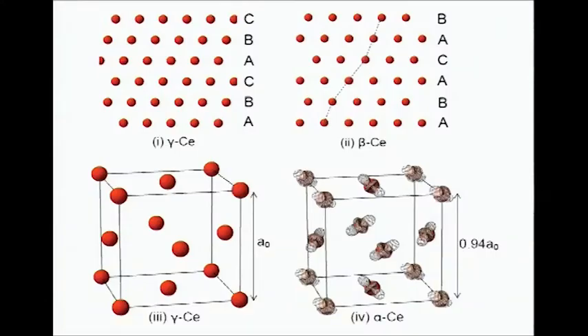Finally, some recent experiments by a Russian group showed that the alpha phase is actually a quadrupole ordered phase, and you get the right lattice constant. They measured this by perturbed angular correlation, and they had to insert a cadmium-111 lattice atom.